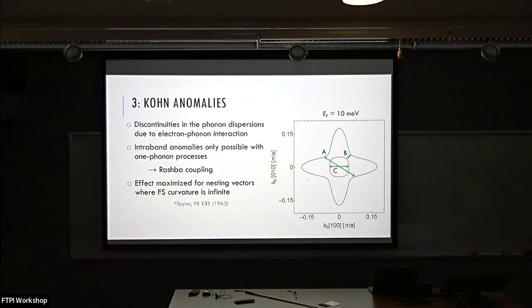And of course, this is known for a long time. The anomalies are maximized if one of the curvatures goes to 0 or infinity. And at the Fermi surface, there is actually a point in this outer one where that happens. The curvature goes from positive to negative, so there has to be a point where it's infinite. And this point corresponds to this A.